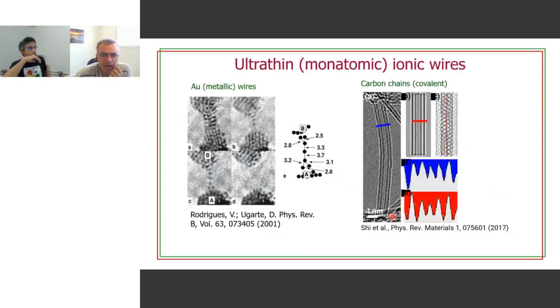to another class of wires, to ionic wires. So the idea is, again, is it possible to create monatomic ionic wires? Well, as I mentioned, in the early 2000s, people already did metallic wires, such as gold and the 5d elements. That is an example of metallic wires, but people were also able to create covalent wires, such as carbon chains. And one of the best ways to stabilize carbon chains is within carbon nanotubes, but people are nowadays able to form and to measure very long carbon chains, up to 6,000 atoms, inside carbon nanotubes.